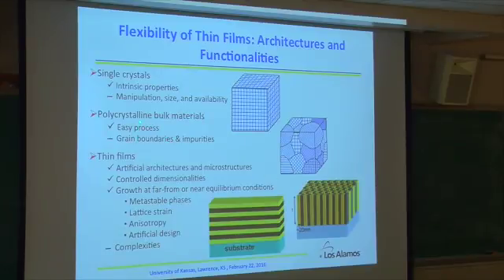But over here, when you're talking about a lot of material, the single crystal material, you cannot have a large size. Of course, some other material like silicon, you have 12-inch wafers, but a lot of material you don't, right? In another sense, a lot of material you even cannot make a single crystal. Just give you one example, like uranium oxide. UO2, you get a single crystal. U3O8, you don't. No one has ever grown this kind of single crystal material.